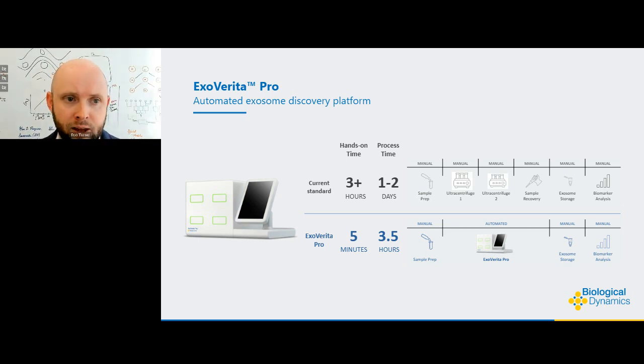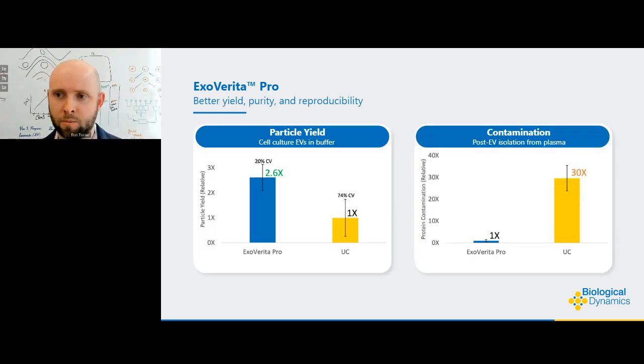And so we've leveraged this and done some comparisons in performance to see how we stack up against ultracentrifugation. And really the key message here is we're getting better yield, better purity, and better reproducibility. There's some data here that shows we're seeing about a 2 to 3x improvement in the actual particle yield when you compare our exosome output to what you'd get off a typical UC run. And in addition to that, we're sitting at about a 30x reduction in protein contamination.